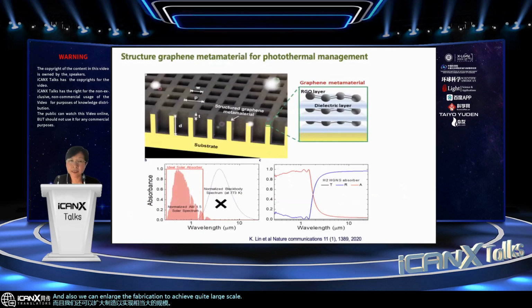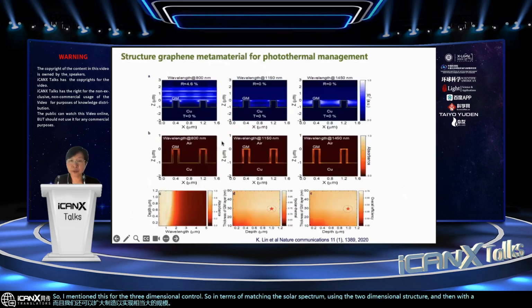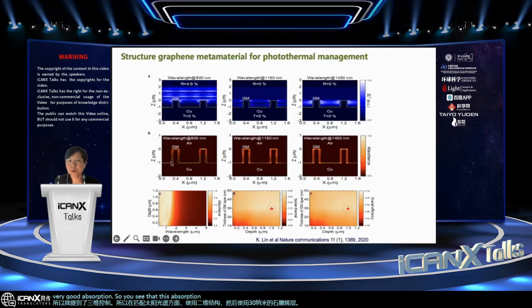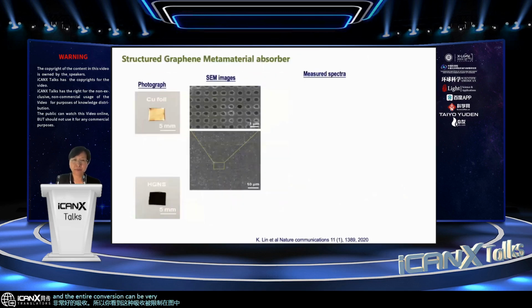So I mentioned this for the three-dimensional control. In terms of matching the solar spectrum using the two-dimensional structure, and then with a 30 nanometer layer of graphene, this one can achieve very good absorption. So you see that this absorption is confined within the graphene layer, and the entire conversion can be very efficient.